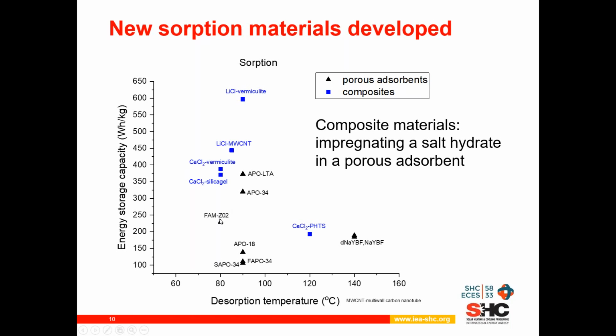The black triangles show the performance of these sorption materials in this application for the pure sorption materials. And the new development now is that to these sorption materials, other materials are being added, salt hydrates, and this leads to a composite material that has better performance. You see this in the performance of the materials with the blue squares, and especially this lithium chloride impregnated in vermiculite material. It has a double performance of the average of the sorption materials.